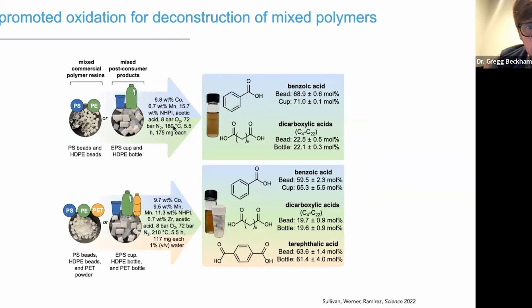This is 5.5 hours, 210C, running at the temperature and residence time needed for the most recalcitrant plastic. You see the polystyrene benzoate yields are fairly similar. The yields for dicarboxylic acids go down by about 10%. And that's because deleterious reactions can consume these and oxidize these to CO2 at these longer residence times and higher temperatures.